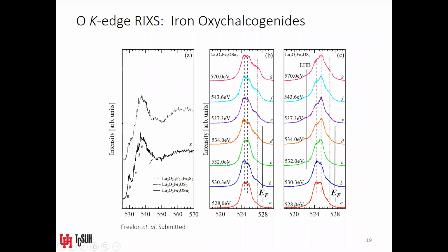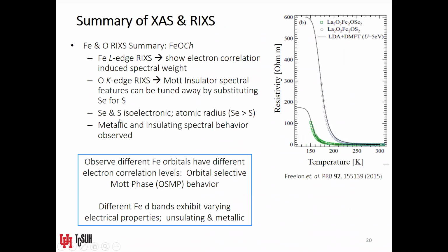Okay, so let me just keep going and attempt to give a summary of some fairly complicated slides I just previously showed. So we performed iron and oxygen edge RIXS on these Mott insulators. And I showed you that for the iron L-edge RIXS, we could see electron correlation in the form of this high energy spectral weight, which we assign to Hubbard bands. This spectral weight comes about because of an excitonic process.